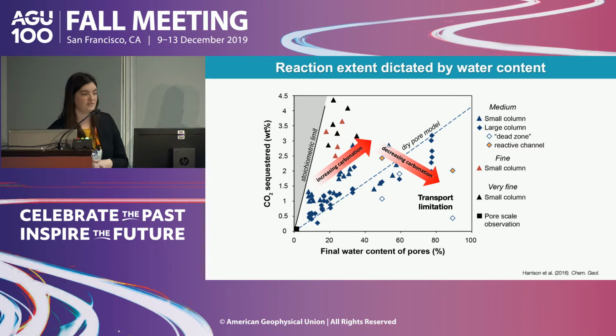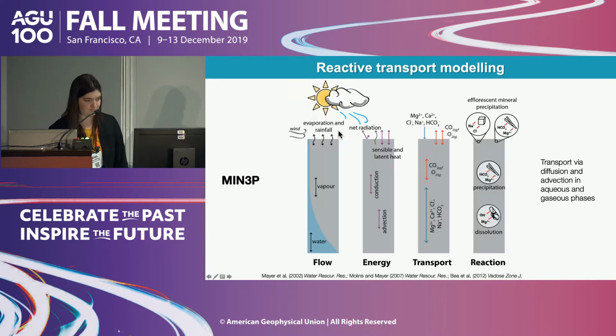In contrast, the reason for lower extent of reaction at low water saturation is less clear. So what we did here is we applied a reactive transport model, Min3P, to simulate our experimental conditions, with the idea being that any difference between our model and our experiments informs us as to the processes that might be missing from our model under these low water conditions.